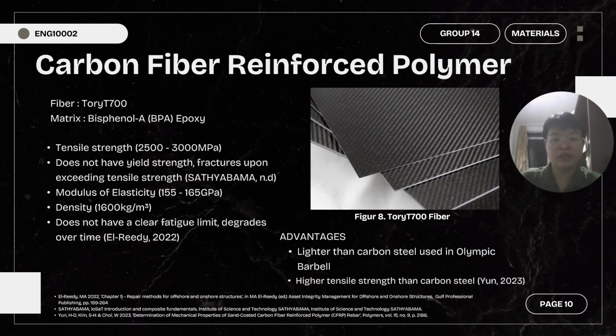Another material class that was chosen is the carbon fiber reinforced polymer. The matrix is a bisphenol A epoxy and the fiber is Toray T700, which is a polyacrylonitrile-based carbon fiber commonly used in sports. By combining these two components, the final composite carries the properties of both the epoxy and the Toray T700 fiber. This material provides a tensile strength between 2,500 and 3,000 megapascals. It does not have a yield strength because carbon fibers behave in a linear elastic manner and fracture directly.